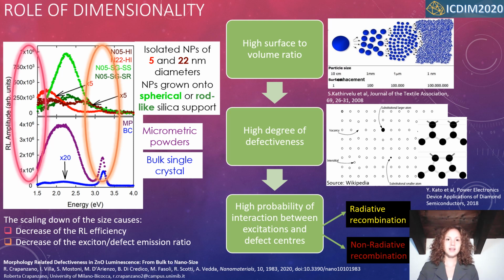Hence, a higher number of lattice sites is exposed. Since interfaces create disorder, the formation of point defects or surface defects such as dangling bonds is favored. Moreover, the smaller the material size, the higher the probability that the excitations reach the surface and interact with its defect states. Consequently, in nanoparticles, the generated excitons recombine preferentially on the surface. This recombination can be radiative with the emission of a photon or non-radiative with the dissipation of the energy by heat.